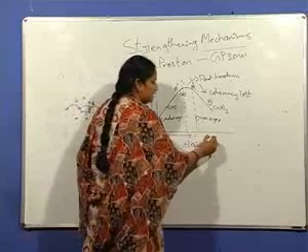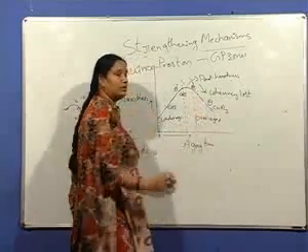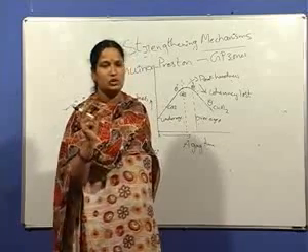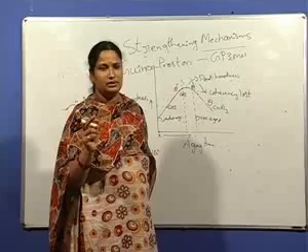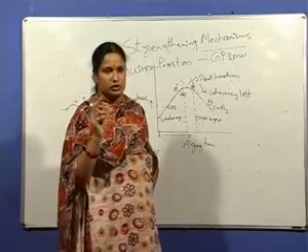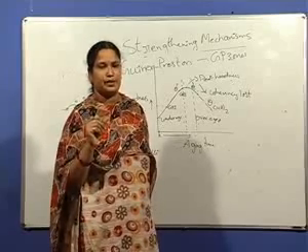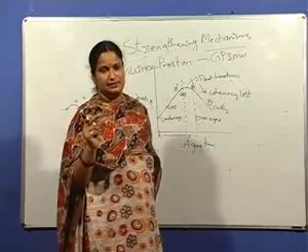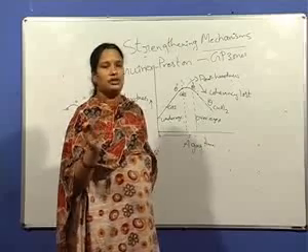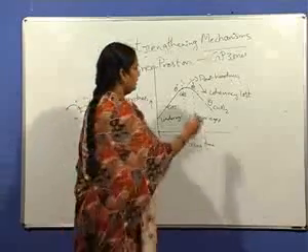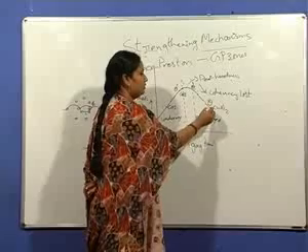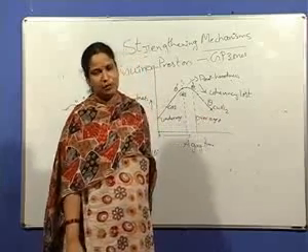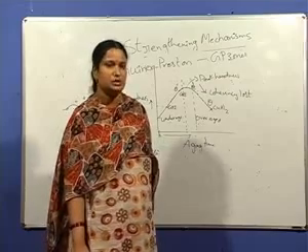With further increase in aging time, the precipitate grows in size, that is, it coarsens to lower the interfacial energy. It undergoes coarsening by solid state diffusion and increases in size. The coherency is lost, thereby the hardness comes down, and an equilibrium phase, the theta phase, forms, that is the CuAl2 phase.